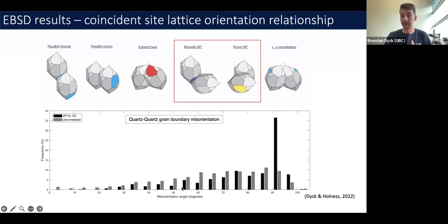on the bottom, this is a histogram showing the uncorrelated. If you take all of the orientations in that map I showed you, and you just took two grains and put them beside each other, what's the likelihood that they have a misorientation angle between them? And if we compare that to the grains that actually do share boundaries, the actual neighboring grains, we can see that the correlated ones are very much non-random, in the sense that there's a high frequency of grains that meet at 90 degrees.